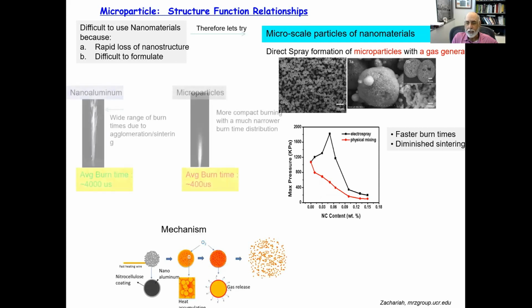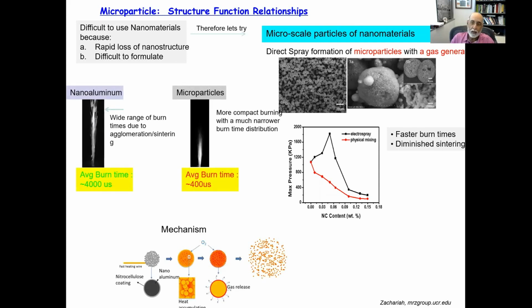So it's just an example of using architecture to perhaps get around the idea of this sintering. And we've looked at the particle sizes that come out, and they are in fact much smaller. So I won't show you those details, but effectively, this approach minimizes the sintering. And you can see the combustion dynamics are very, very different. Here is a flame with nano aluminum with an average burn time of 4,000 microseconds. And these microparticles are a factor of 10 faster. The flame is much more compact, it's much more dense, it behaves completely differently. And this is just architecture. Chemistry is really the same in all these systems. And we've spent a lot of time looking at other systems that behave similarly.